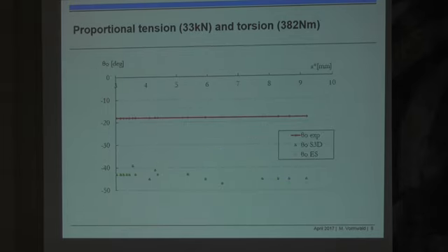However, if we now investigate the predicted angle and the orientation of the real crack where it grows, then there is a considerable difference. We would have expected for this proportional case something around 40 degrees. However, we found in our experiment only about 20 degrees, which means that we have not found the final solution for this problem, and work must continue in a certain way.